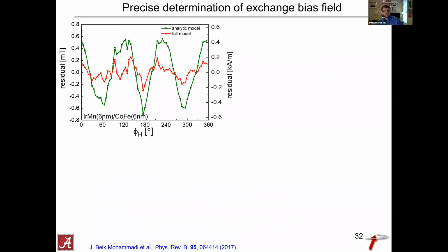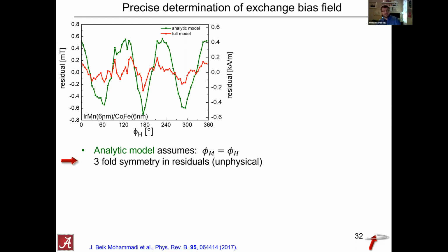However, what I always tell my students is, instead of just looking at the data like I showed before, you should always look at the residual. How does the fit actually deviate from the data that you measured? That's shown here. In the analytical model, you see this kind of systematic angle dependence, which tells you something isn't quite right with that analytical model. Whereas with the full model, you get what you should expect. You basically just get random noise in your residual. The reason for that is the assumption of the analytical model is that the magnetization is always aligned with the external applied field, which leads to, interestingly, something that looks like a threefold symmetry, which in this case is rather unphysical, I would say.